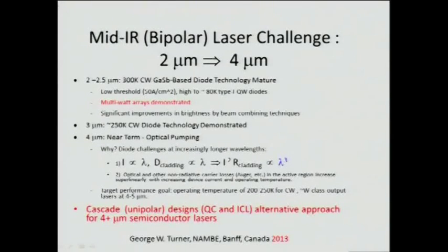A good result: he reported lasing at room temperature CW, with a threshold current as low as 50 amps per centimeter squared, very high T sub 0 at 80 K, and multi-watt output. And of course, as we know, when we go to higher wavelengths from 2 microns to 3 microns and up in this antimonide system, we run into problems: we need thicker cladding layers and higher resistance, and then heating of the substrate and Auger recombination problems.